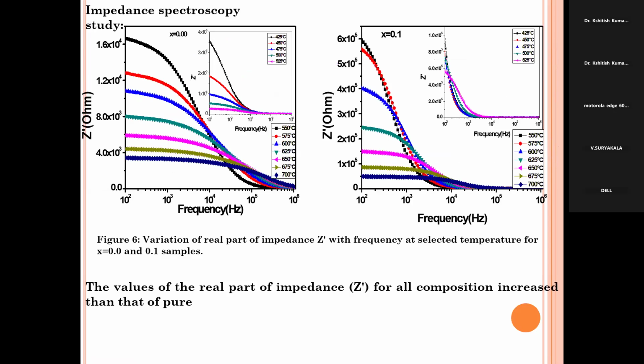Then we have to find out the relaxation, means impedance spectroscopy of the material. Impedance means the resistance. As I told, grains are present and grain boundary is there, and this grain and grain boundary is related to the resistance, and it is also related to the conductance of the material. How do we find out? We have to find the real part of the impedance and the imaginary part of the impedance. Here we have shown 0.00 and 0.1, and what I got is that the impedance of the doped material is more, which means the resistance is more, so we thought that the conductivity may decrease, and due to the lower conductivity the material gives better ferroelectric property.